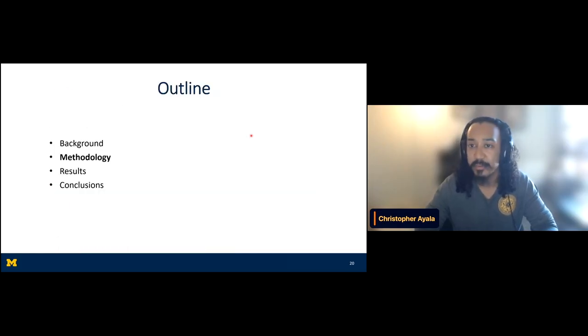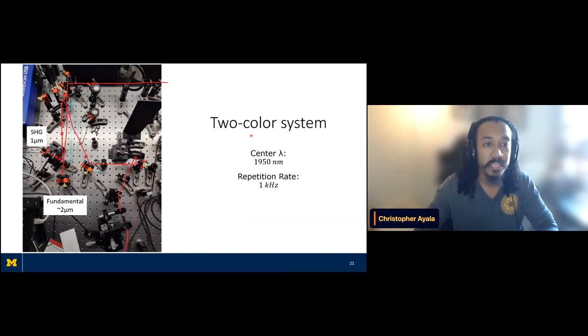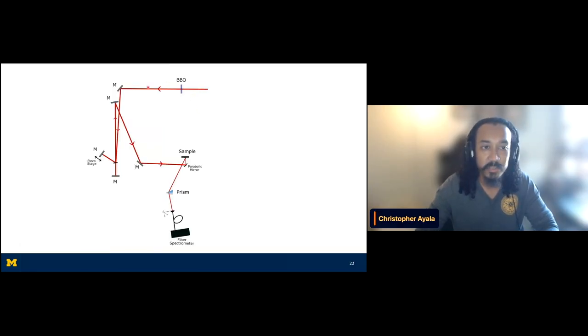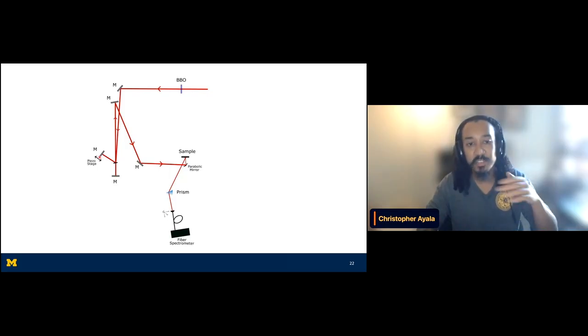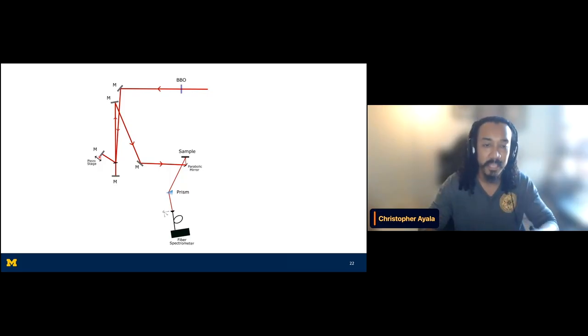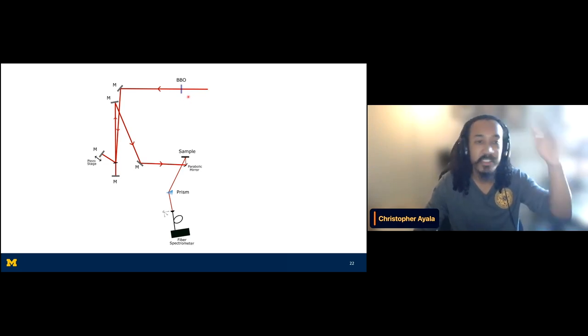So how do we do these harmonic generation measurements? To go back just a little bit, we had a collaboration experiment where the incoming laser was about 1950 nanometers with a repetition rate of about 1 kilohertz. What I mean by two-color system is that you take a BBO crystal, you have a fundamental of about 2 microns, and you interact it with a BBO crystal, which puts out the second harmonic generation at about 1% of the total output. When you interact the fundamental and the second harmonic generation pulses, you are actually breaking the inversion symmetry of the laser, and in so doing, you now have broken inversion symmetry in the system, and that allows you to have both even and odd order harmonics. To have only single color or only odd order harmonics, all you have to do is remove said BBO crystal, and you have a single color system again.